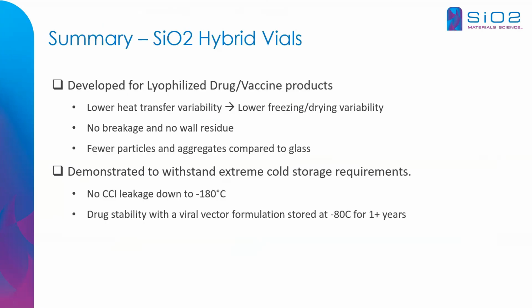So just to wrap up what we presented, and I know I've given a lot of material here, we developed a container for freeze-drying lyophilized drugs and also for vaccine products. Lower heat transfer variability means lower freeze-drying variability. We've shown no breakage and no wall residue, so very good, attractive-looking lyo cakes. And also important, fewer particles and aggregates compared to glass after the freeze-drying cycle. That was done with both a model solution as well as an IVIG drug.